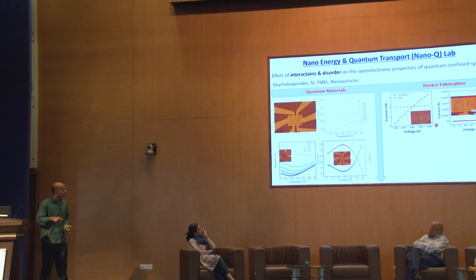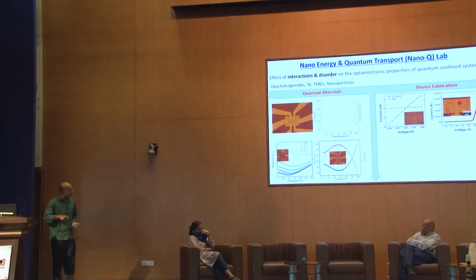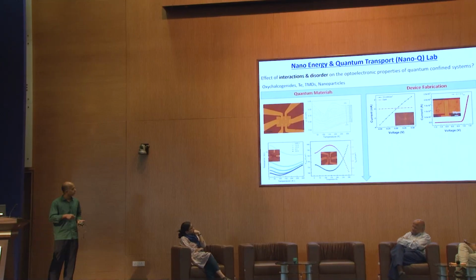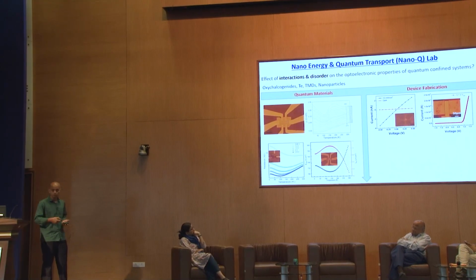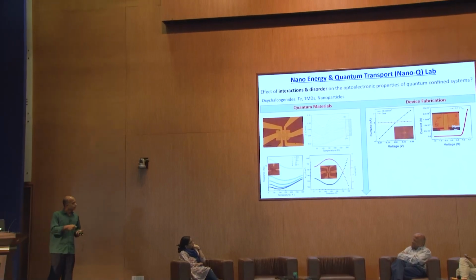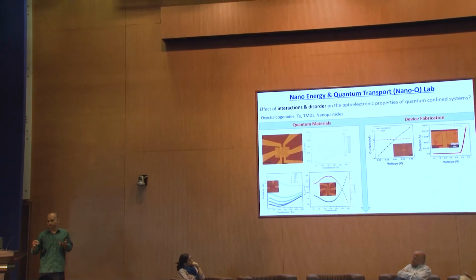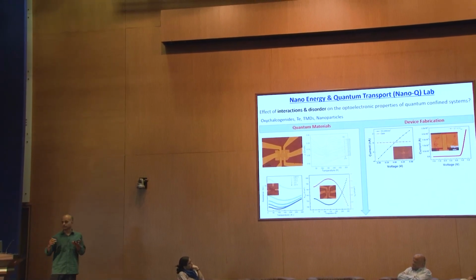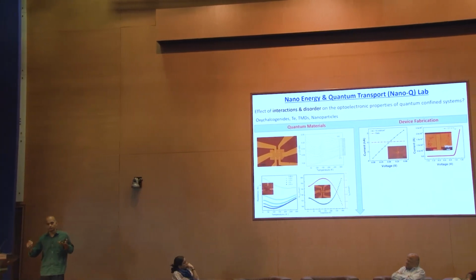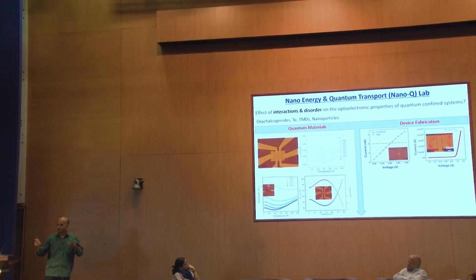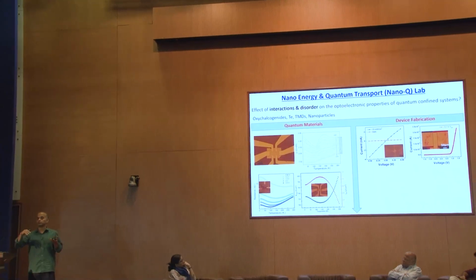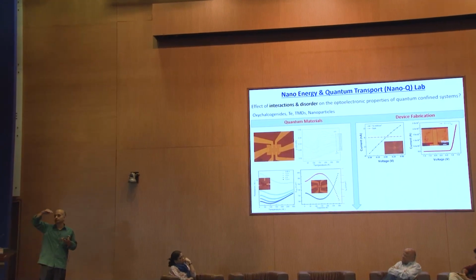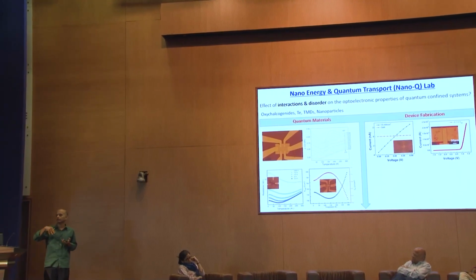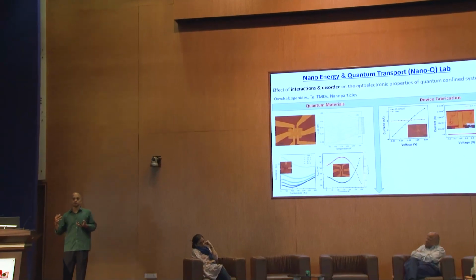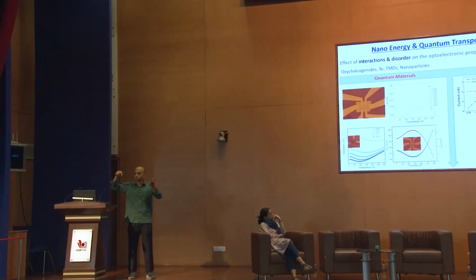This is another one. This is a TMD layer which you cannot see. It's underneath this hBN, hexagonal boron nitride layer. So here we actually made a van der Waals contact. So basically it's again a field effect transistor type geometry. It has a gold contact, but the gold contact is not deposited on the material, rather the material is transferred onto the prefabricated contact, and that can give you a van der Waals type junction. So basically the electrons will now tunnel and you'll get a very low contact resistance.